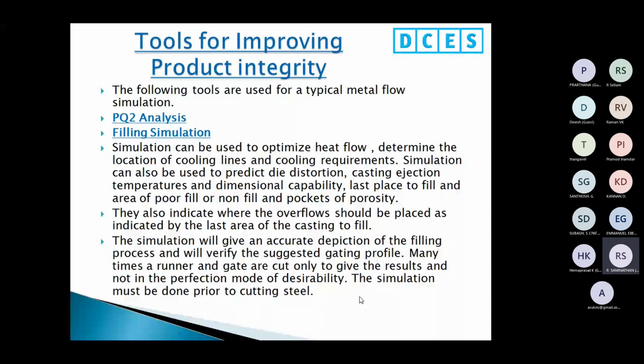They also indicate where the overflow should be placed as indicated by the last area of the casting fill. So when we try to place the overflow in the casting, this will show where is the end of the fill. The simulation will give an accurate depiction of the filling process and will verify the suggested gating profile. Many times a runner and gate are cut only to give the results and not in the perfection mode of the desirability. The simulation must be done prior to cutting steel. So here I suggest to use the filling simulation before starting the tool manufacturing.